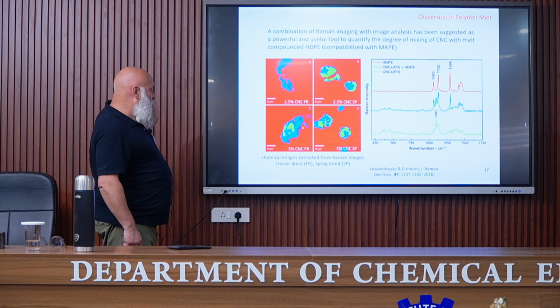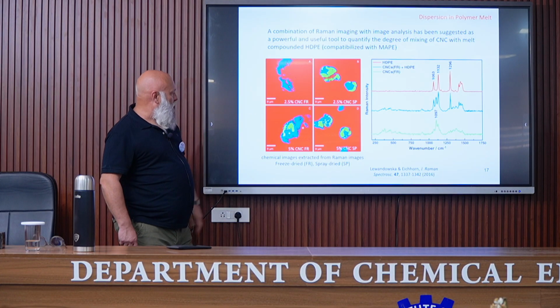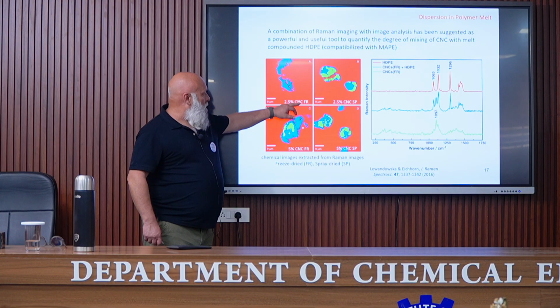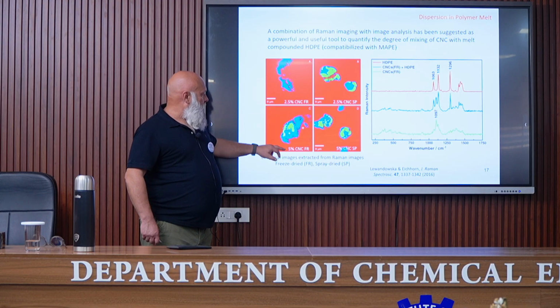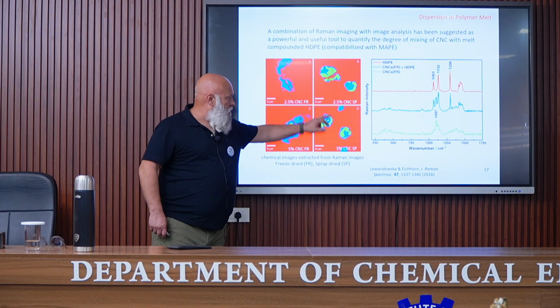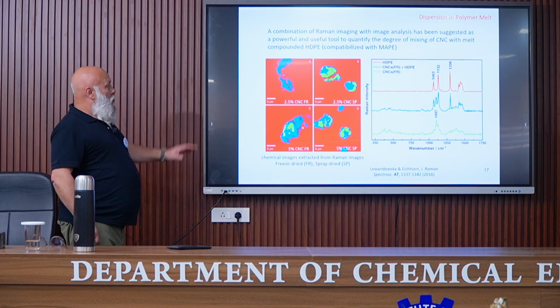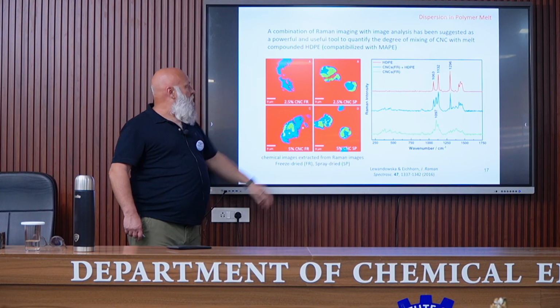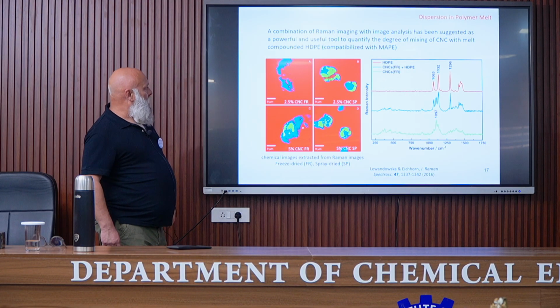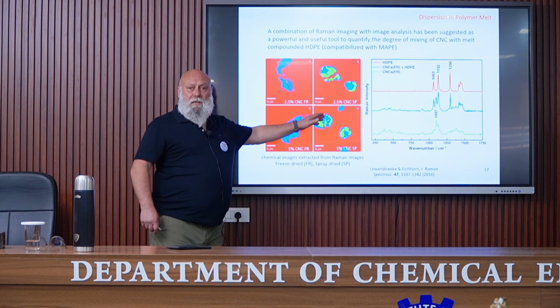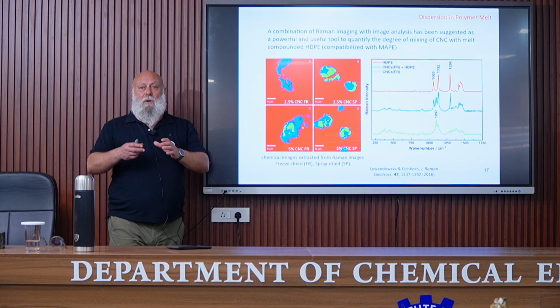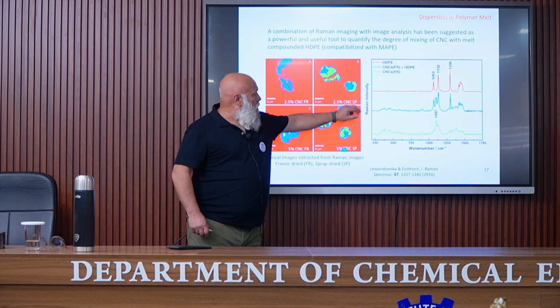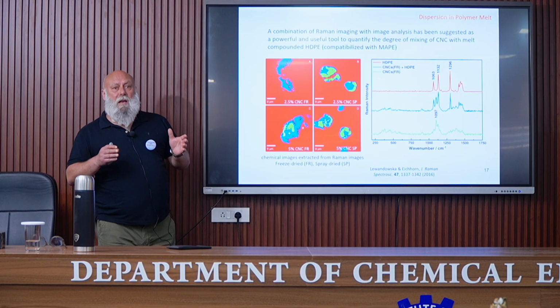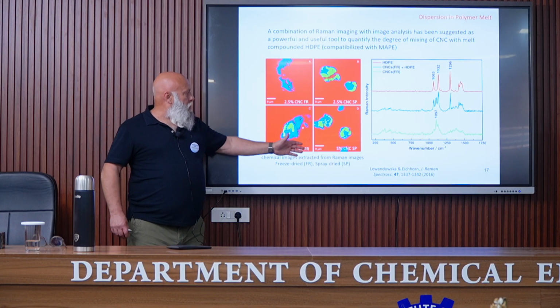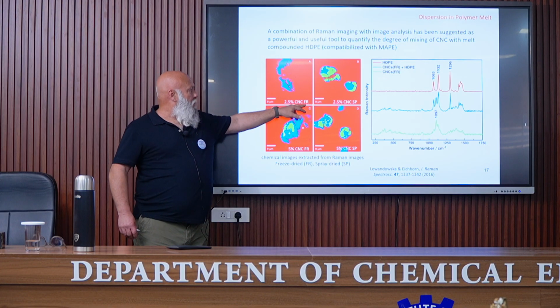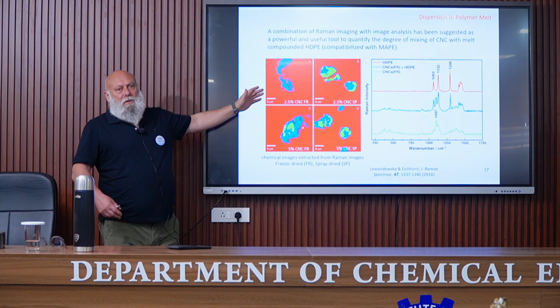And so he reports this chemical image, which was extracted from the Raman image, for freeze-dried nanocrystals, here 2.5% and 5%, and spray-dried nanoparticles, 2.5 and 5%. In red, we can see the matrix, high-density polyethylene. In green, it corresponds to cellulose nanocrystals, meaning that the green part consists of aggregated nanocrystals. And in blue, it is a mixture of high-density polyethylene and cellulose nanocrystals. So what we can conclude here is that in this case, 2.5% freeze-dried, the dispersion was better. It was not perfect, but it was better.